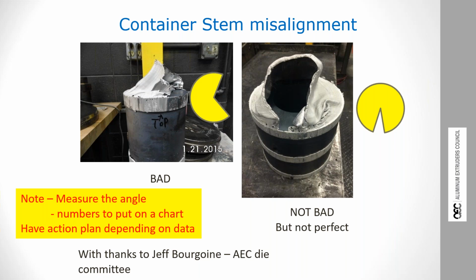Because in this top left-hand picture, we have serious steel-on-steel contact occurring where the dummy block is running down the container. This will wear the dummy block and then maybe lead you to attempt to weld it up. And it will also gouge out the container, which will lead to bellying, both of which Danny has showed you is not good. You can also see here clearly, as Danny pointed out, this is much thicker here because that's where all the aluminum is.